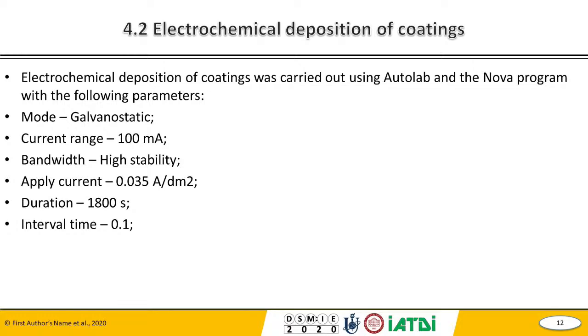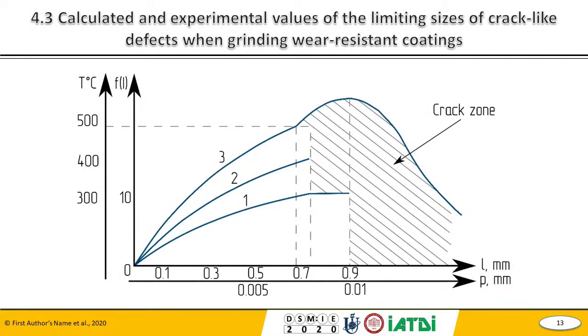Next slide. Summarizing the previous, we present an analytical model showing the relationship between the temperature during the processing of wear-resistant coating of cylindrical surfaces, coating processing parameters, geometric parameters of coating defects, and in addition the characteristics of the treated coating. As can be seen, with the indicated axis of these parameters during coating treatment, the wear-resistant coating is destroyed. Next slide, please.